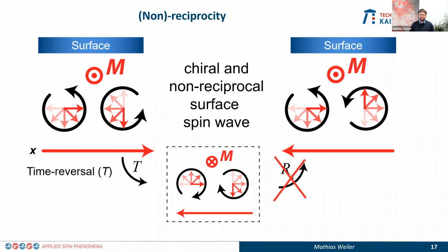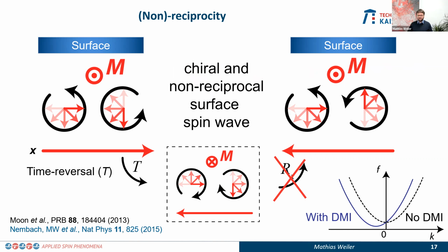And that changes if we introduce the surface. If you introduce the surface, then the symmetry operation here, this rotation about the x-axis that would be needed to go from this image to this image, you would have to basically rotate it about this red arrow over here. And that doesn't work anymore if there's a symmetry breaking along this up direction. And that means that in general, surface spin waves can be chiral and non-reciprocal. You know that from the Damon-Eshbach waves, that they already can be non-reciprocal. And one other famous example of non-reciprocal surface spin waves is the spin waves with Dzyaloshinskii-Moriya interaction, where the DMI at such an interface or surface breaks the inversion symmetry, and that can lead to a non-reciprocal wave. And that means that the spin wave dispersion can shift from the standard parabolic behavior shown here in the black dashed lines to a shifted one, this blue one over here.